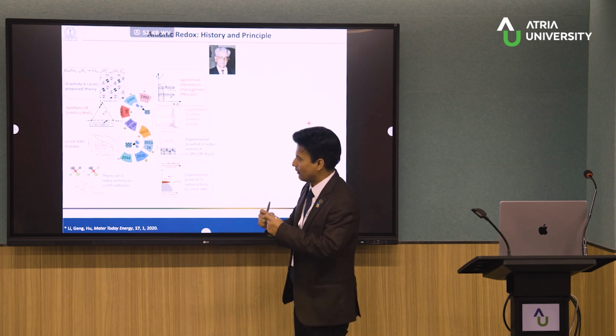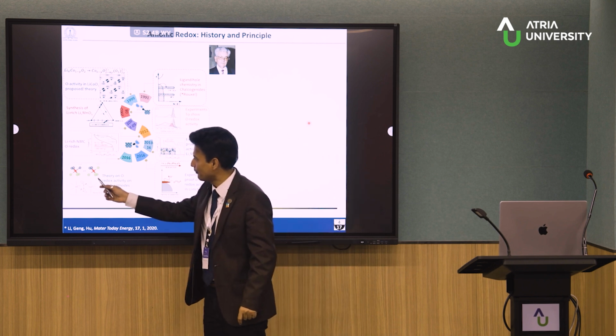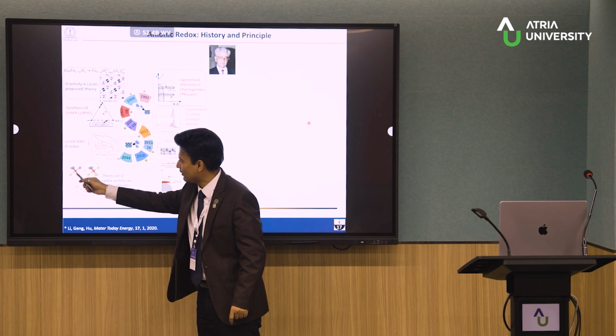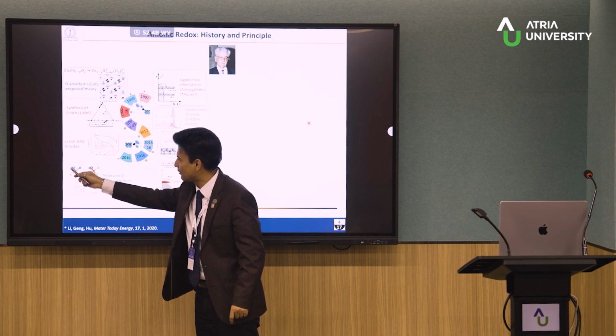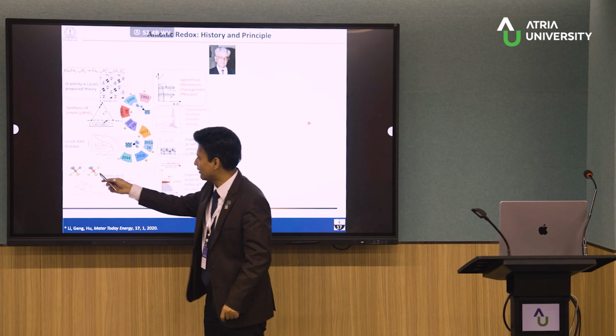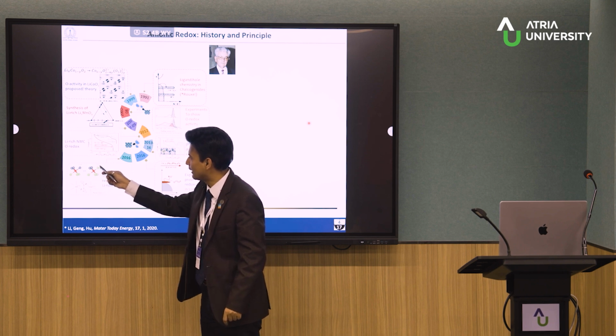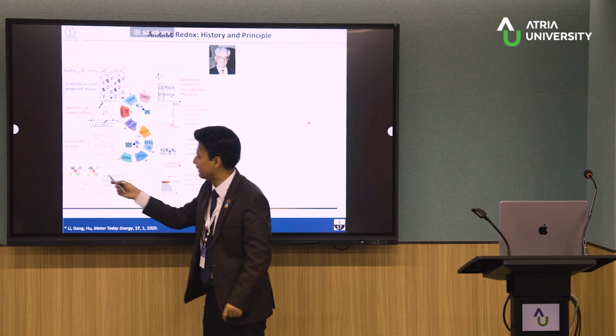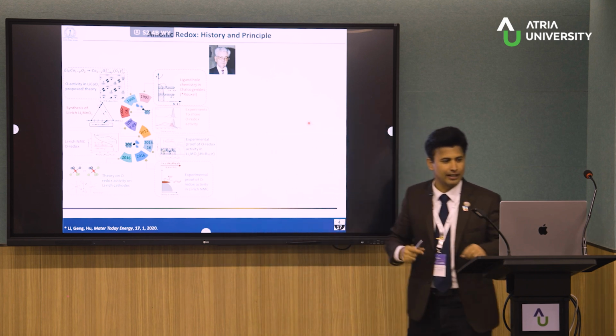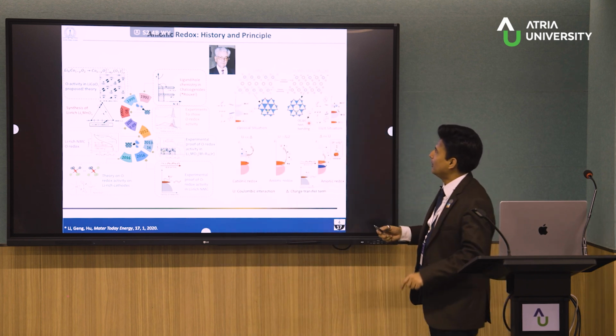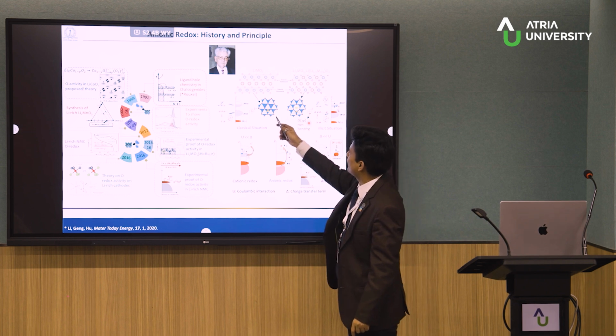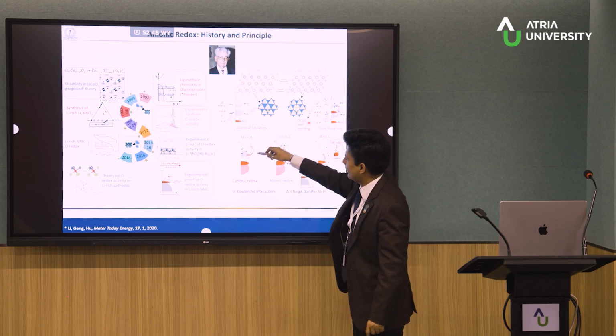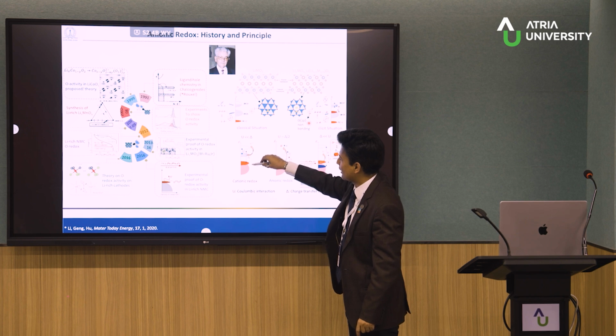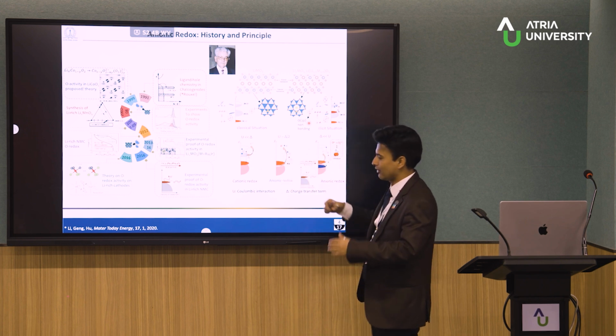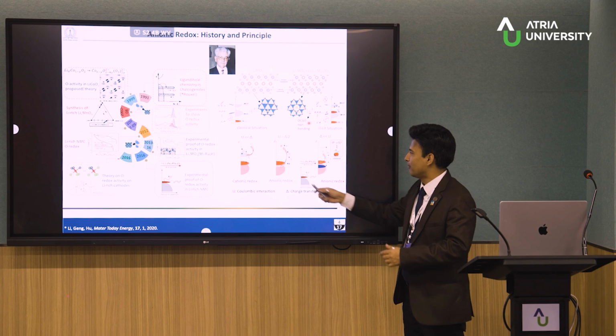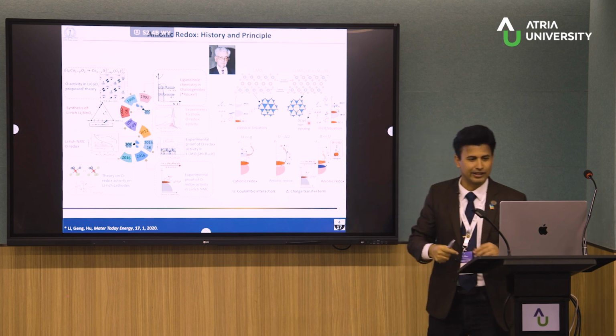So pretty much, when we have a lithium-rich system, in one case when there is no lithium-rich, one side there is only lithium, one side there is transition metal. When there is lithium-rich, transition metals are less, and there is more lithium. As a result, the local bonding environment is different, and we can get some different electrochemical properties. Now, in cationic redox, the transition metal changes, the oxygen does not. In the case of anionic redox, there is a band overlap. As a result, before the transition metal, some oxygen redox can also occur.